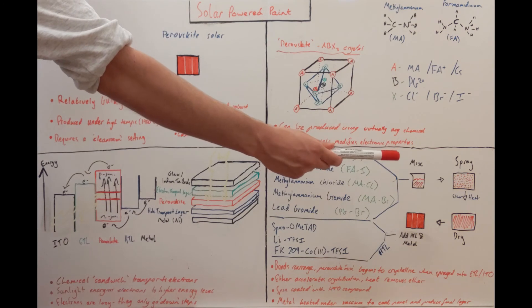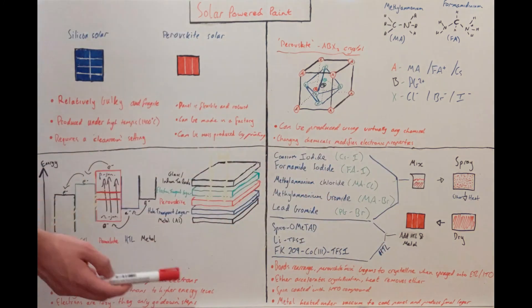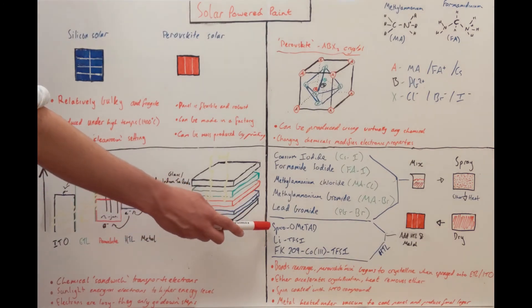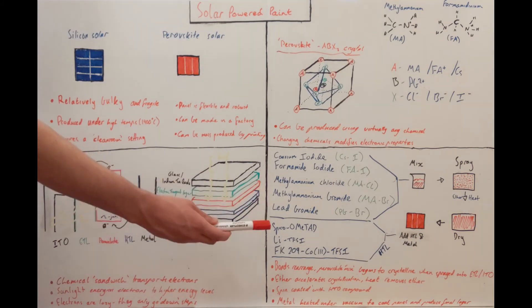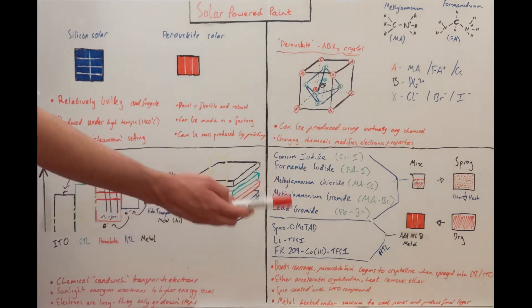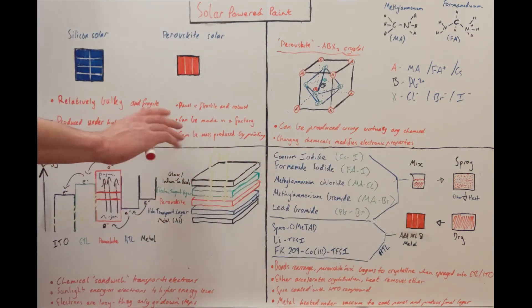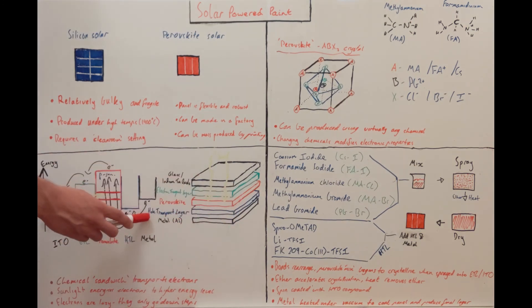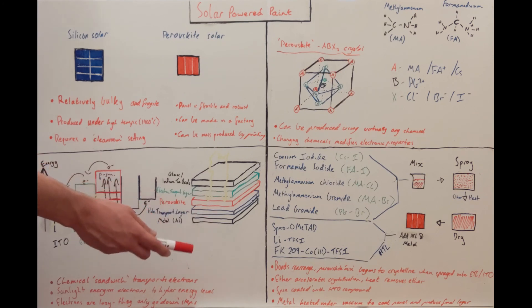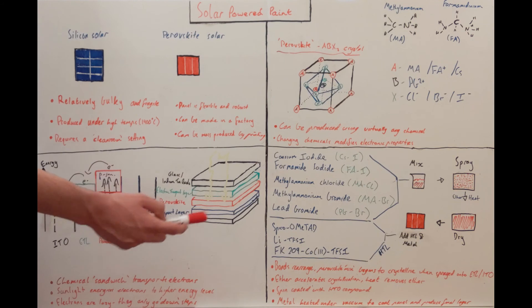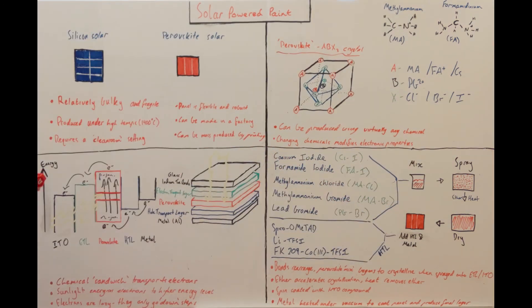Once enough crystals have formed, the panel is heated to remove the ether. Then the hole transport layer is formed by mixing three complex organometallic compounds, which are very effective at performing that role. A small amount is dripped onto the panel and spun at around 3000 RPM to produce an even coat. Finally, to produce the metal layer, metal is heated to a very high temperature in a vacuum, which releases metal atoms that deposit onto the top of the panel. That gives us the complete perovskite cell.